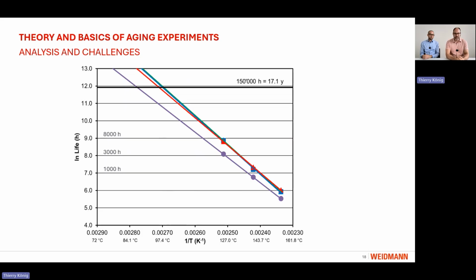One challenge here is really that these points have to be accurate, because you're extrapolating to much longer times. What happens if this point here, for example, was not here, but a little bit down? You see that the slope of this curve changes, and then the error up here can be quite significant. Therefore, it's important that everything is verified and no failures are made.